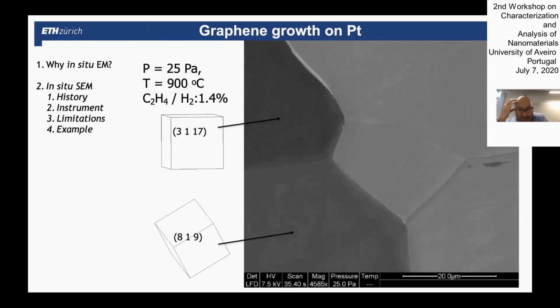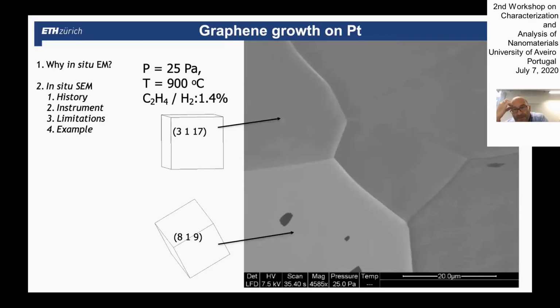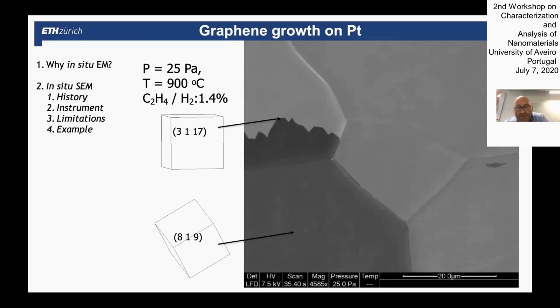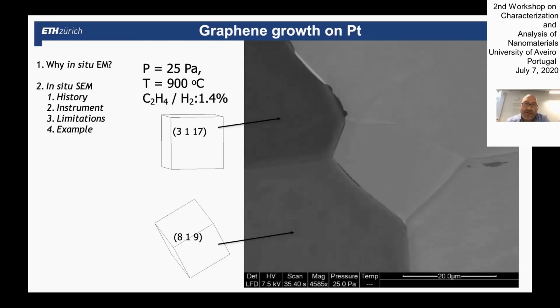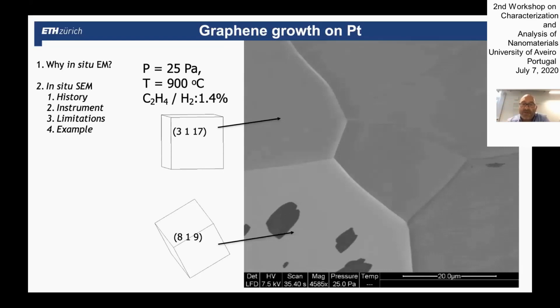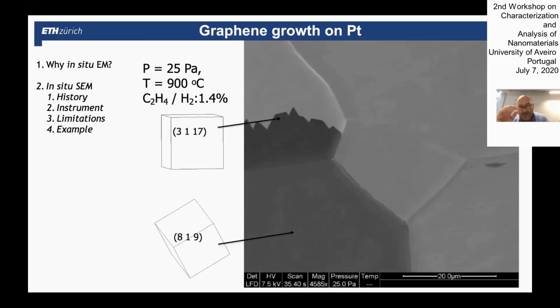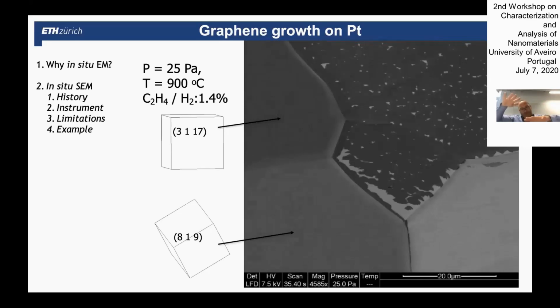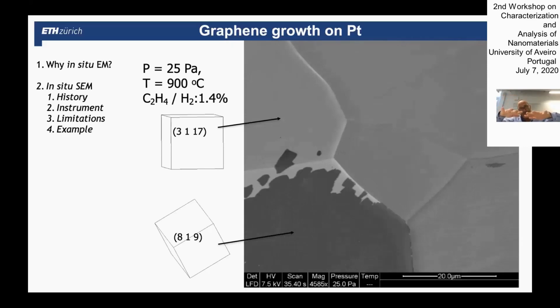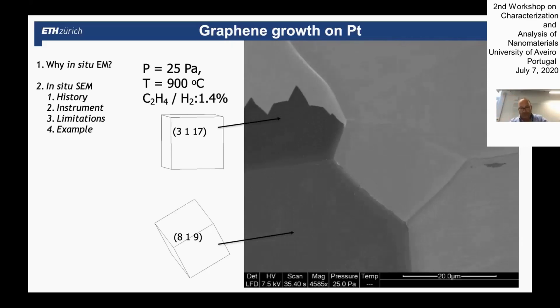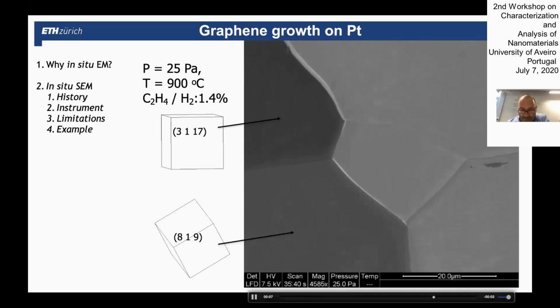So the video is running at a constant temperature. And the time is running, of course. The video is running here faster than real time. So we have always hydrogen and hydrocarbon. So there's always a competition between a bit of etching and growth. So by changing the ratio between hydrocarbon and hydrogen, we can balance it such that there is no growth or very slow growth. And so in these conditions, there's very slow growth. Down there you see the scan. Each scan takes 35